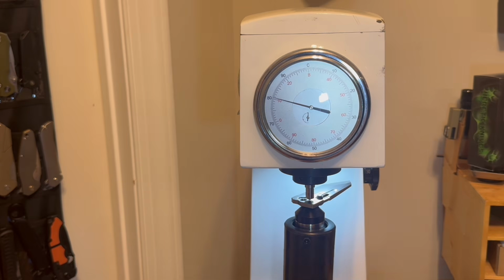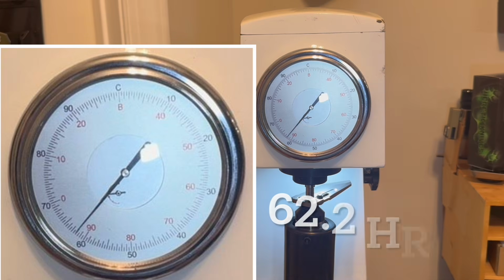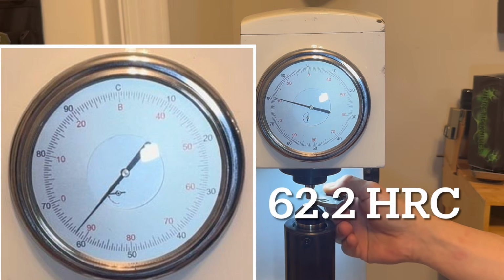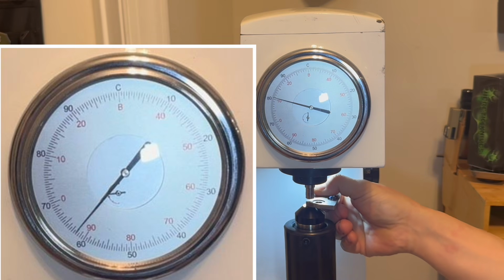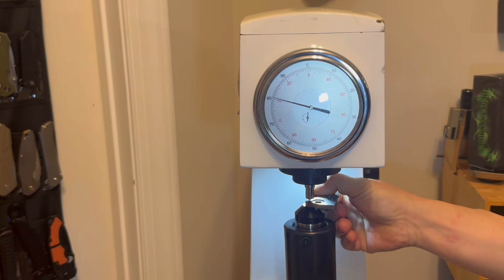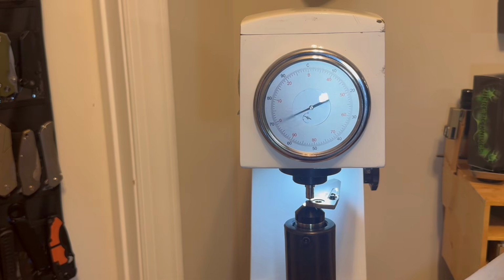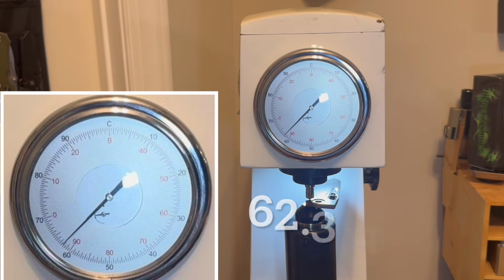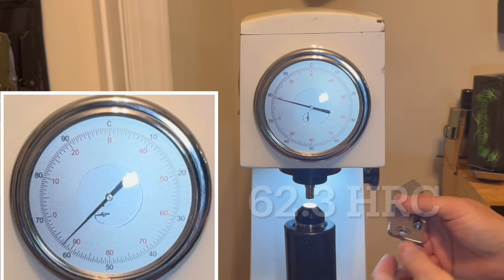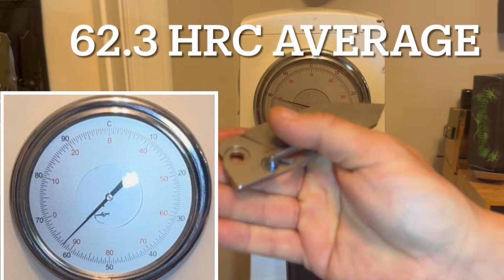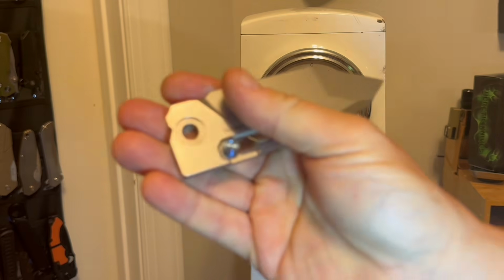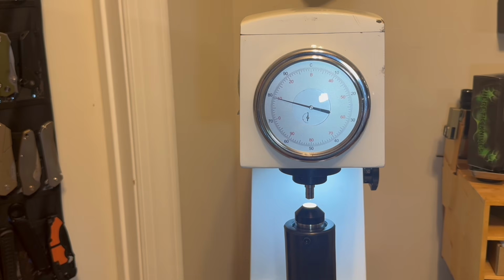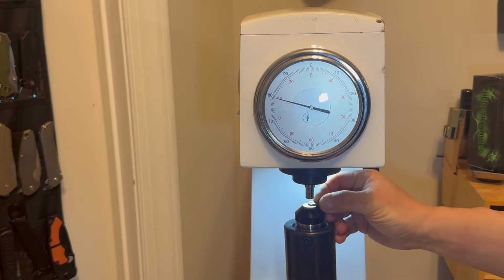And this is significant because to get M390 to above 62, we got 62.2 on the second poke. So to get it above that level, it requires pretty serious cryogenic treatment after the quench and both tempering cycles. 62.3 on the third poke, which gives us an average of 62.3. That is pretty impressive, and now we're moving on to test that lock bar plate.